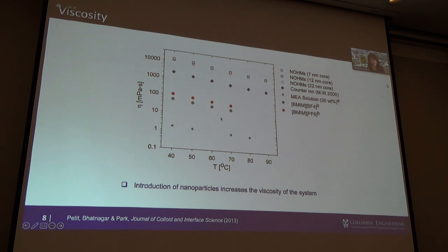So my colleagues like John Brennecke at UT Austin, working on ionic liquid, were very brave and said, well, we can tune maybe the hydrogen bonding network and reduce the viscosity, and they did a really good job significantly reducing viscosity of ionic liquid. In my case, I thought it would be much harder for us. Although we can tune the hydrogen bonding network and many other things to reduce the viscosity, we didn't think it would be worth it for us to work that way.